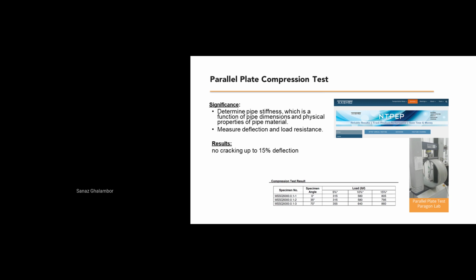This was done with no cracking, no breaking. So we continued up to 10% and finally to 15% of deflection. Again, no cracking, nothing. It shows that this system has very good ductility, although it is very hard and strong. It has enough ductility and it is not brittle at all. So it can go up to 15% deflection without breaking or cracking.